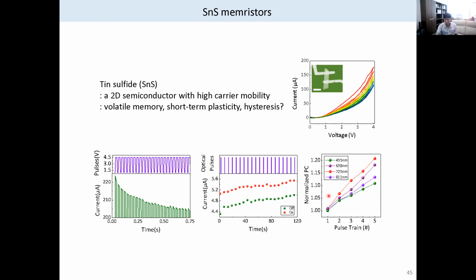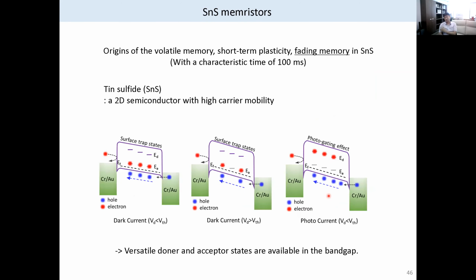So this is what I mentioned, the high dimensional state. Here I summarized volatile memory, short-term plasticity, and this fading memory. In physics, we say hysteresis. The conductance or the resistance depends on the measurement history. And the characteristic time is quite slow, about 100 millisecond. 100 millisecond, it is not femtosecond or nanosecond. In physics, we say it is somehow related to charge trap, because excitation, phonon, and non-radiative decay are governed by picosecond and nanosecond dynamics. So somehow this is related to charge trap.